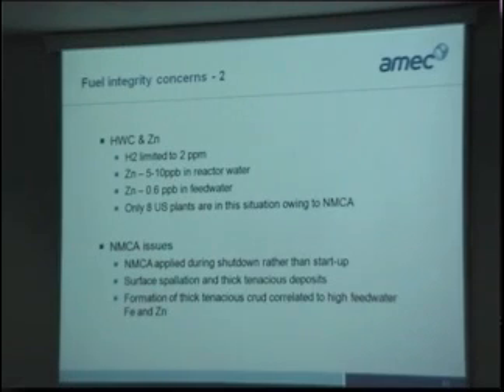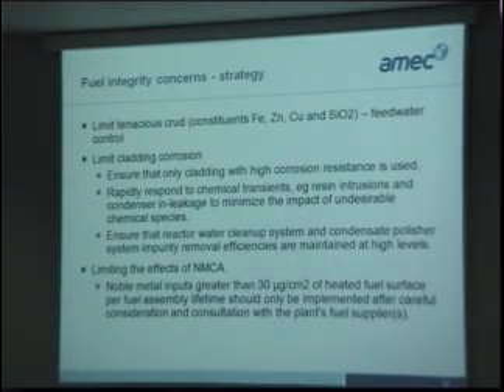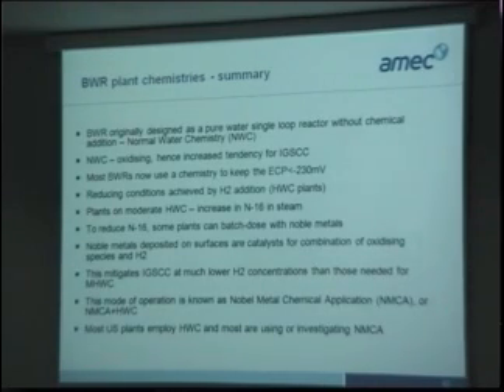So for hydrogen water and zinc, we limit hydrogen to 2 parts per million. We have zinc in there between 5 and 10 in the reactor water and 0.6 in the feed water. A few plants are in that situation. But here, with noble metal addition, that's applied during shutdown rather than start-up. We've got surface spalling and thick tenacious deposits, and the formation of thick tenacious crud is related to high water iron and zinc. That's just the strategy. I'm going to skip that and just summarise the plant chemistry.